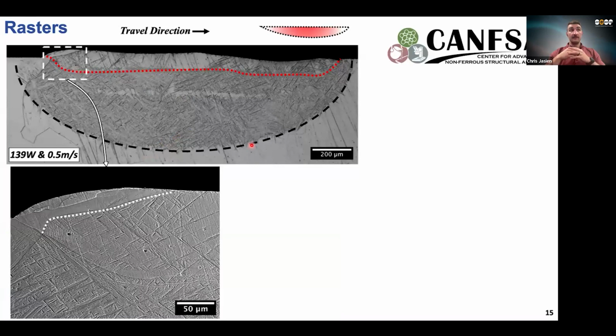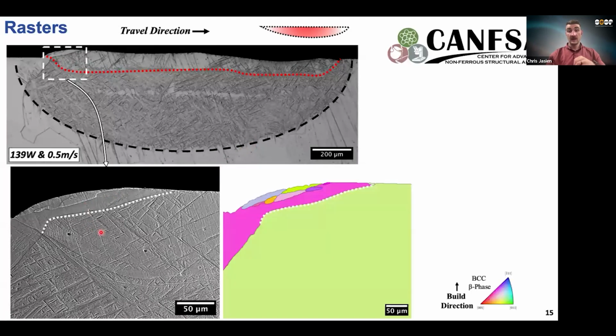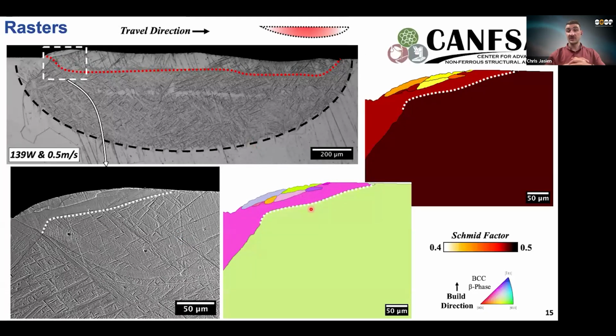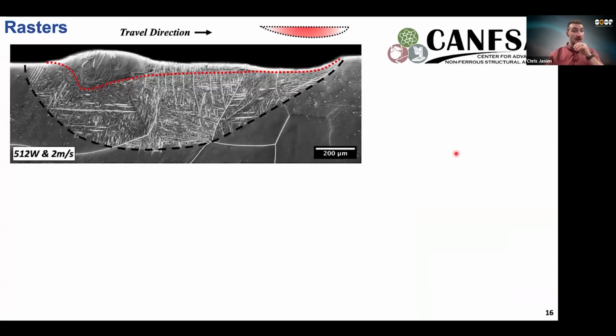And so now, looking microstructurally at what's going on, we looked at the beginning of this raster to investigate it further. And what we see again is a very delineated region that goes from non-transformation to significant amounts of transformation. When we dive into some more characterization, we see that this region is separating two grains. And just to correlate that to Schmid factor, we again see that the higher Schmid factor grain is the one that has transformed more.